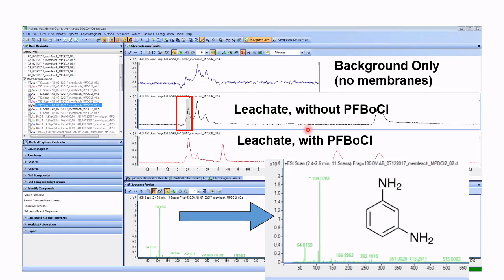So when we ran those same samples on a mass spec, the same samples that we saw, okay, now there's something coming off of the membrane, we see it on this instrument that can't tell us the structure, but we still have those samples. Now we can run those samples on a mass spec, and we can go peak by peak and figure out what the structures of those are.